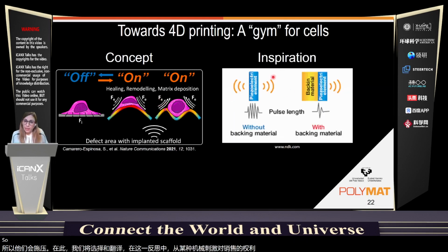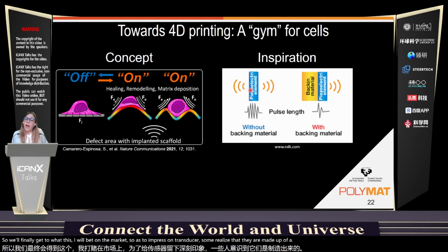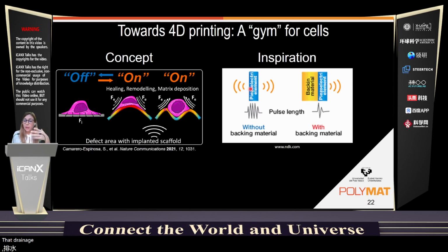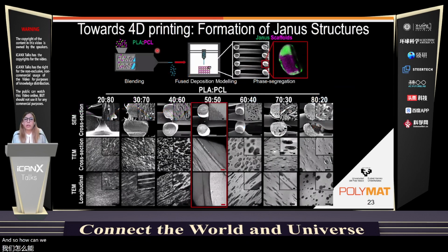So we looked a little bit at what is out there on the market, so ultrasound transducers, and we realized that they are made up of an active element that readily vibrates upon application of ultrasound and a backing material that dissipates these waves. So when these two come together, what you get is a pulse and controlled wave in response to the ultrasound application. And so how can we do that practically? We looked a little bit at the physicochemistry concepts, and we chose two biocompatible and biodegradable materials, PLA and PCL.